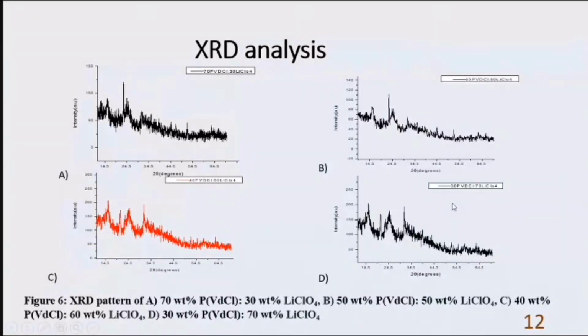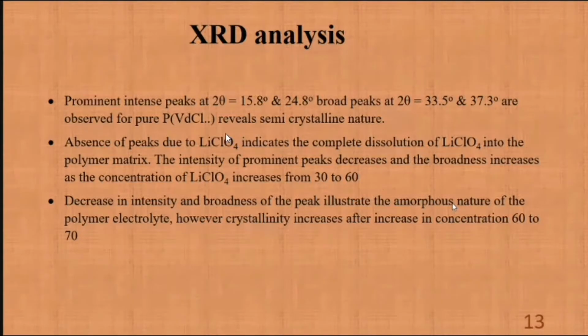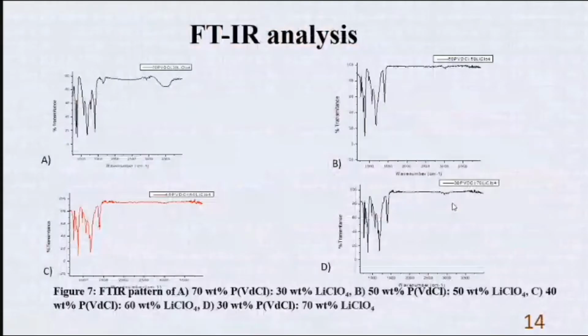Okay, here our results are here. The XRD results show that the amorphous nature of the polymer is increased on increasing the salt. The pure polymer is semi-crystalline in nature, while the conducting polymer is amorphous in nature. Here the results are shown. The values are shown here.